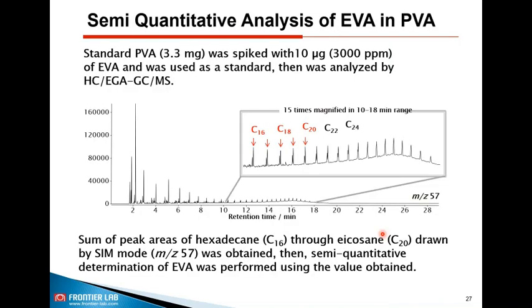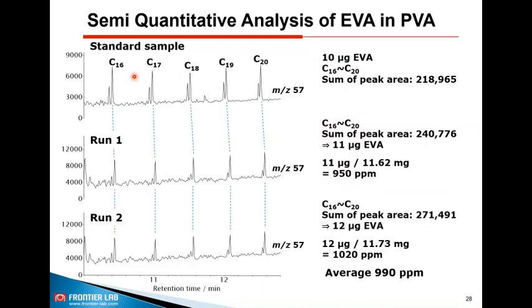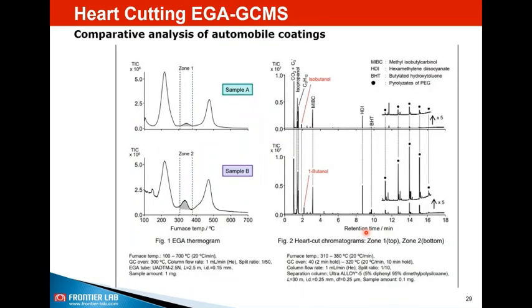Then we confirmed this by spiking the polyvinyl alcohol with ethylene vinyl acetate, a real sample. Then we could see again these extra saturated hydrocarbon peaks. So that confirms this is coming from ethylene vinyl acetate only. Then we also tried to do a kind of semi-quantification for this turbid sample, where we found it is having close to 1000 ppm of ethylene vinyl acetate. That means now the customer can do a kind of protocol where they have to rinse the facility to ensure that their EVA concentration is less than 1000 ppm to avoid any kind of turbidity in future PVA manufacturing. So this is how it is helping, the heart cutting GCMS.